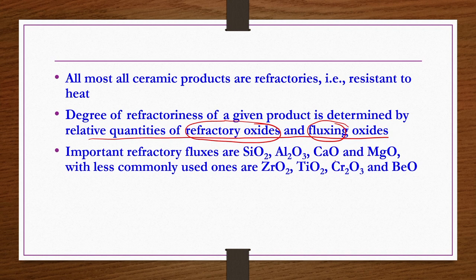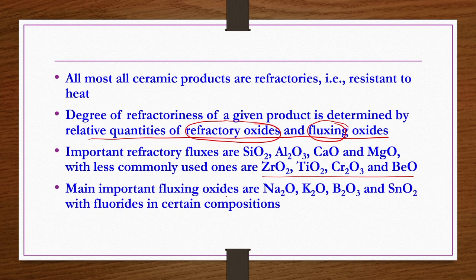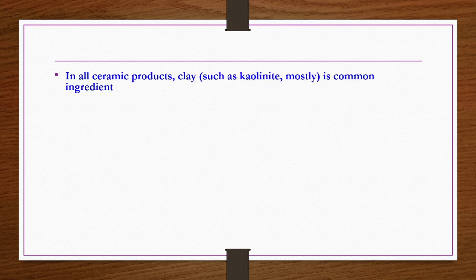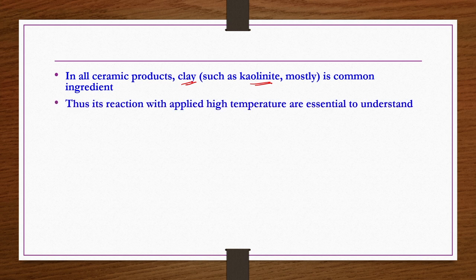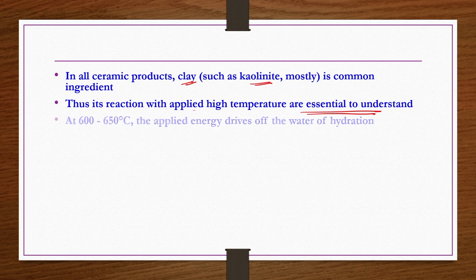Important refractory fluxes are given here, but there are some less commonly used refractory fluxes also, given here. The main important fluxing oxides are these, with fluorides in certain compositions also possible. So what we understand until now is that in ceramic products, clay such as kaolinite, mostly though not the only one, is a very common ingredient, and thus its reaction with applied high temperature is essential to understand. At 600 to 650 degrees centigrade, the applied energy drives off the water of hydration, that is, the dehydration reaction takes place.